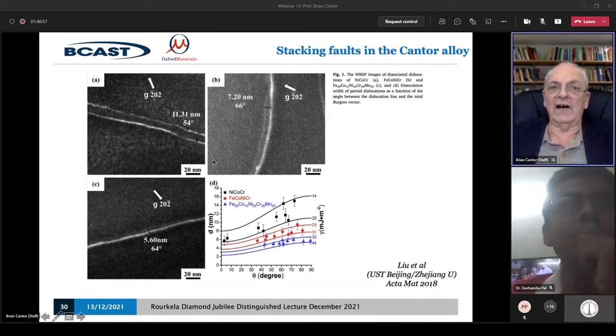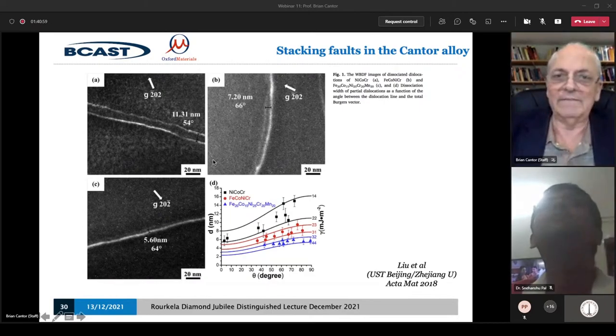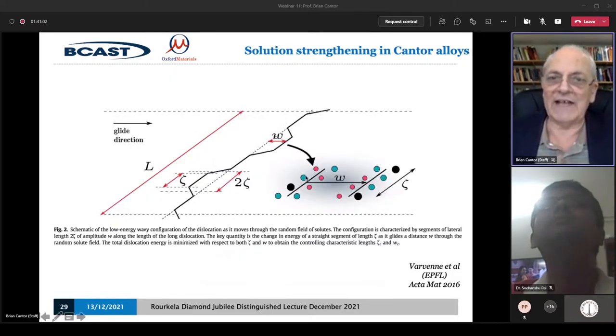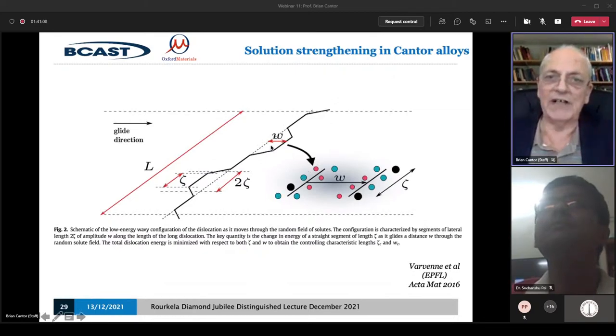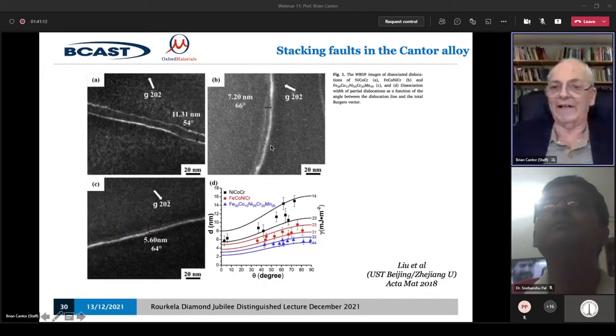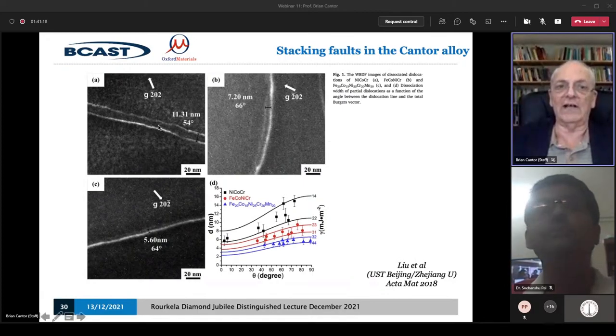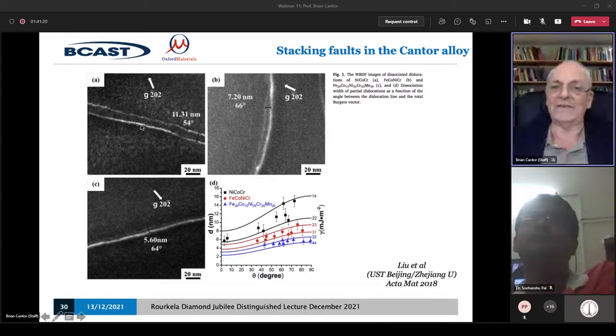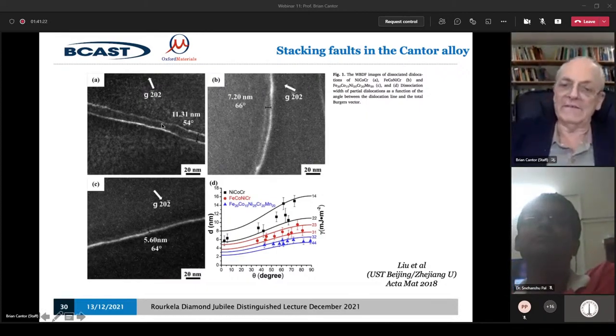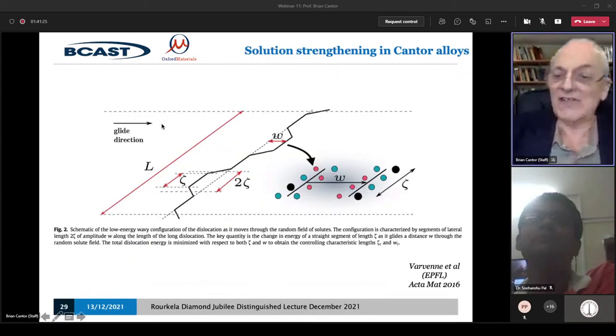But in our material, each atom has a different local structure. So as you move along the dislocation, the stacking fault energy is different at each point. It's not the same everywhere, as it was in pure copper or pure gold, where the partials are the same distance apart all the way along. But here they're different. So that's the first thing to notice.